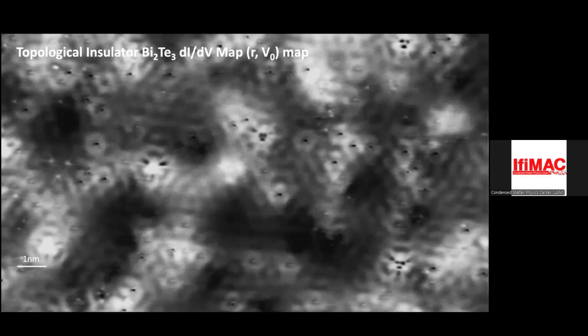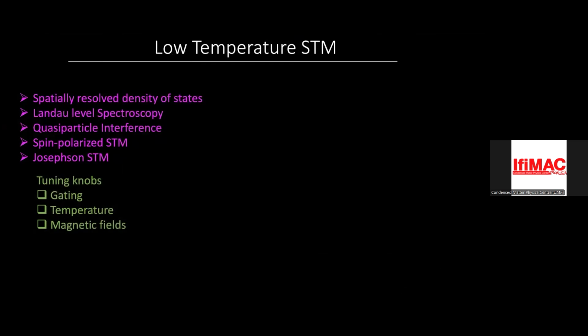You can also do dI/dV maps and look at quasi-particle interference. This is a dI/dV map on bismuth telluride, which is a topological insulator. And you can get band structure information from such maps.